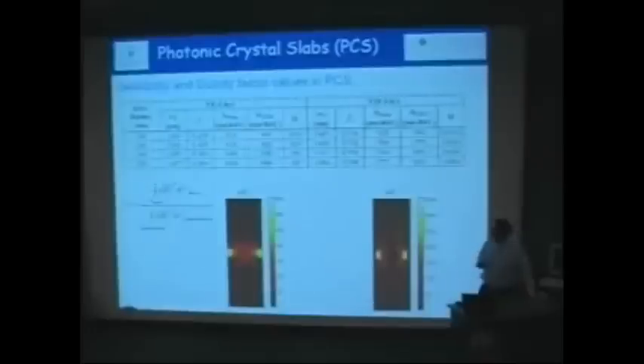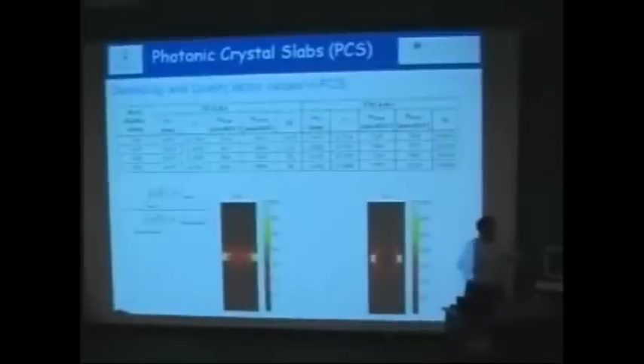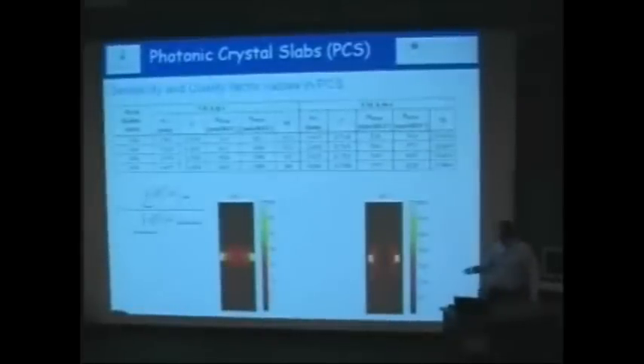I wouldn't have too much time to go into details. I'll just briefly mention that this is a large table that tries to compare them. If you compare them, you could see that the TM-like resonances that are shown over here give us better sensitivity and better quality factor. So they're superior as compared with the TE-like resonances, and if you want, we could go maybe later into the details. But this is the conclusion of the analysis, that it's always good to work with TM-like resonances when it comes to biosensing.